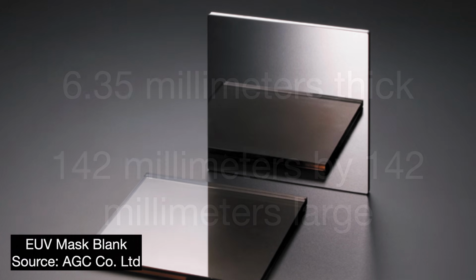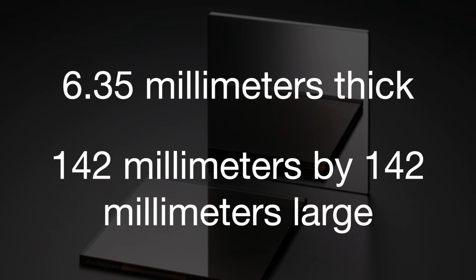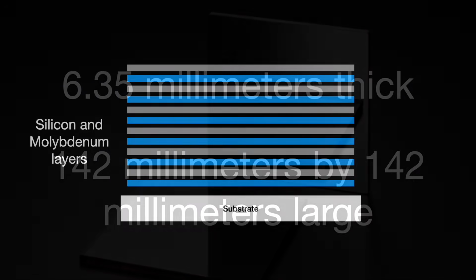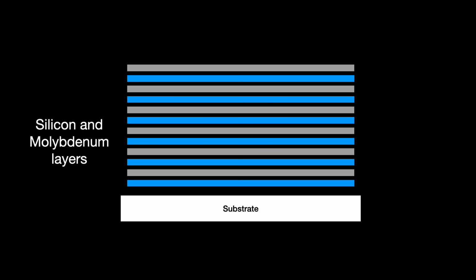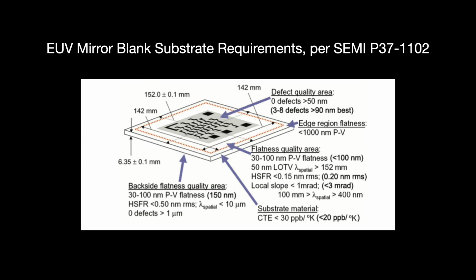Based on the SEMI P37 standard, it is about 6.35 mm or a quarter of an inch thick and 142 mm by 142 mm large. At its very top is the mirror layer, a multi-layer Bragg reflector with 40 to 50 alternating layer pairs of molybdenum and silicon. I talked about this before. The mirror layer sits on top of what has to be a very thermally stable substrate. According to SEMI standards, the substrate can only expand or shrink some 6 to 10 parts per billion for each Kelvin. Otherwise, you get print errors.